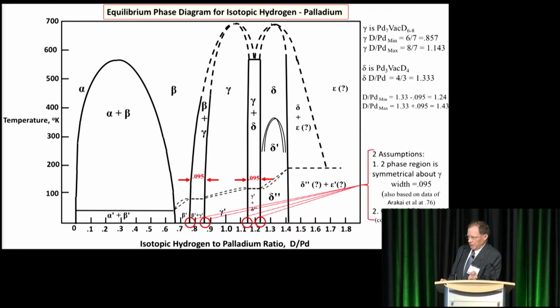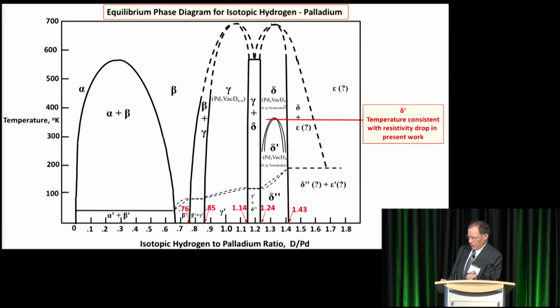I'm going to also skip all this detail about exactly the locations of these two-phase regions. But the most important thing is that I have experimental evidence that supports this delta to delta prime transition. Basically the difference between delta and delta prime is the location where the deuterium finds its home, whether it's at the octahedral site as a delta phase or at a tetrahedral site as a delta prime phase. That shift is supported by a temperature measurement in my data, which I'll show.